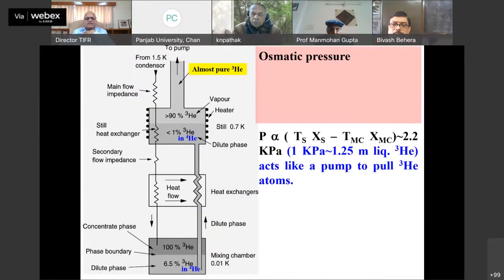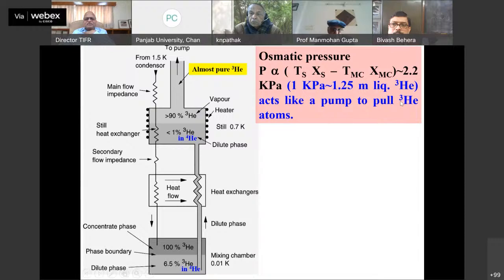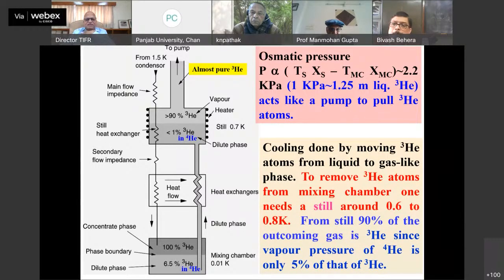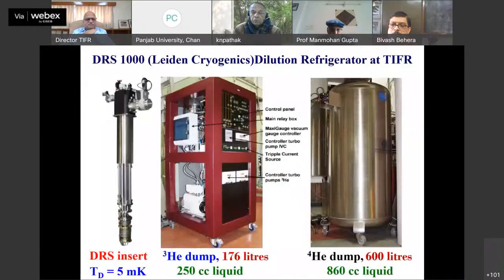And the osmotic pressure can be as high as 1.2 meters of liquid helium-3. So it's able to pull this helium-3, and then this helium-3 which comes to the pump gets back into the system. So you have a continuous refrigeration. So cooling is done by moving helium atoms from the liquid to a gas-like phase. To remove helium atoms from the mixing chamber, one needs a still around 0.6 to 0.8 Kelvin. So 90% of the helium gas is coming from here to the pump, and that is being recirculated again. So one can reach about 3 to 5 millikelvin at the mixing chamber at the bottom.